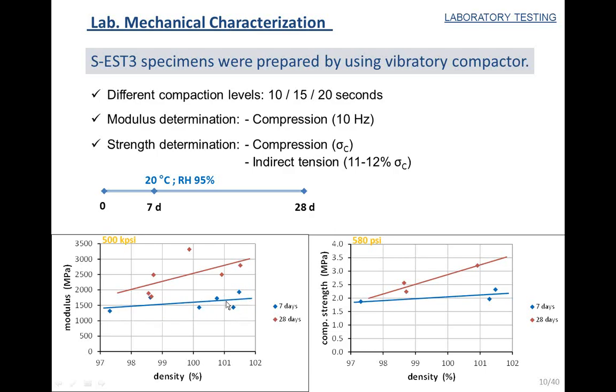This is after 7 days, and then you can see here in red the evolution after 28 days. So at the beginning of the test we were expecting a modulus around 2000 megapascal. The requirement of the in situ density is 95% of the optimum density. So this point, 95%, was the target in the field. So this is the most important thing.